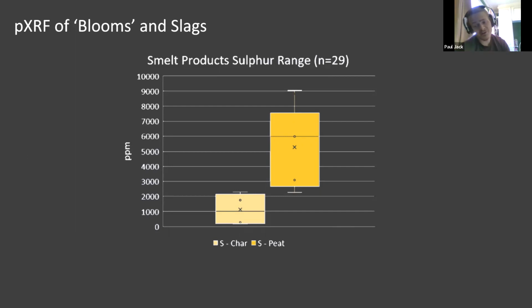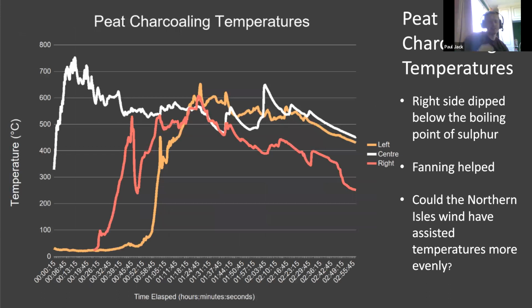The only way this would have been introduced, of course, is the fuel. But if we look at the charcoaling of that fuel, its production, we might expect that this would have driven off a lot of the sulfur. Sulfur turns into a gas at around 444 degrees. So if we draw a dotted line here, you can see that one side of these charcoaling pits was letting us down. In this instance, it's the right-hand side that's failing to maintain temperatures above this threshold.